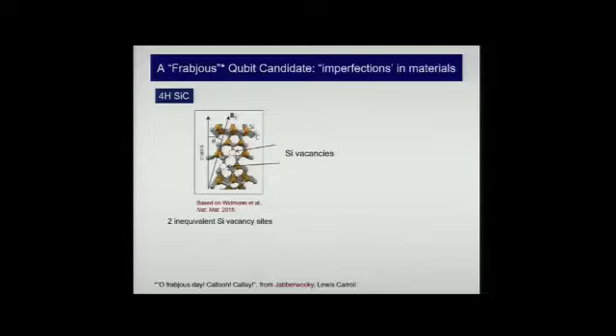So what we see here is a structure. This is a C-axis 4H silicon carbide. And what we've done is ruin the perfection of 4H silicon carbide. We've wrested two silicon atoms out of their rightful places, and what we have are silicon vacancies. Now, because of this particular structure, these two vacancies are in slightly inequivalent sites. That means those two vacancies, they're both vacancies, but they see a slightly different electronic environment, and you'll see how this translates to the performance of these vacancies.